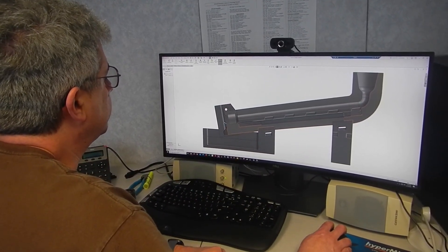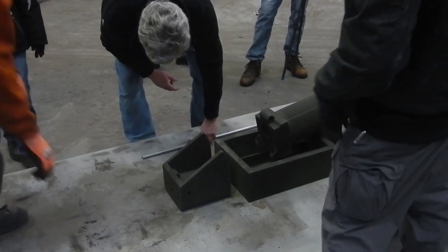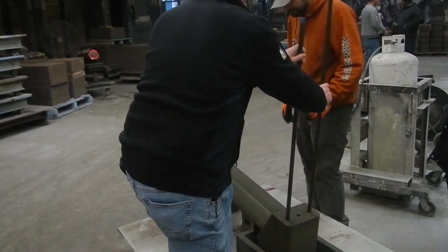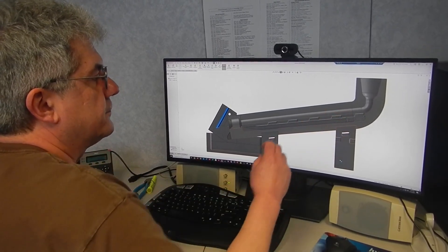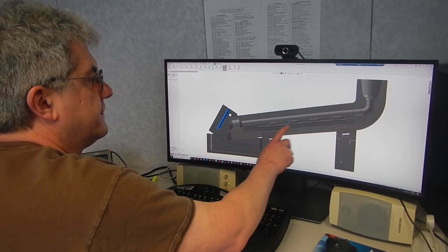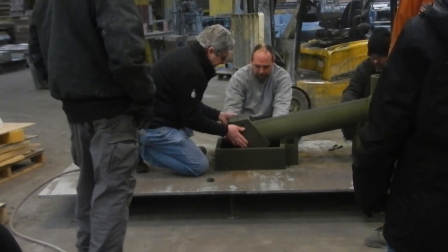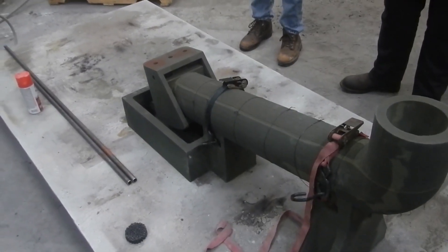we have a valve. Using simulation, we can determine when these blades will solidify and they don't need risering anymore. Design the riser large enough so that it will stay liquid long enough that we can drain it after the blades have solidified and it's done risering. That should give us just the blades and all the risers are drained into the ingot molds.